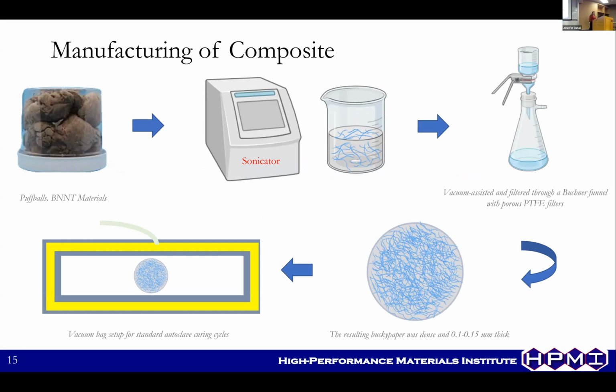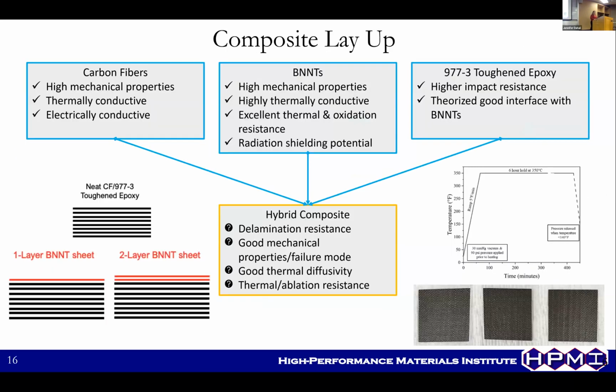So we have taken these BNNT puffballs. This project used unpurified puffballs, which is why they look brownish in color. Highly purified BNNTs are a white, translucent color, so they have some interesting optical properties that I've been discussing with some of your professors. We take these puffballs of BNNT material, sonicate and break them up into a well-dispersed solution. We use vacuum-assisted filtration, and we create what's called bucky paper, or a veil of BNNT. Then we can use it in a standard autoclave curing cycle, standard composite processing from there. So it's handleable. It's like a regular sheet that you can easily handle.